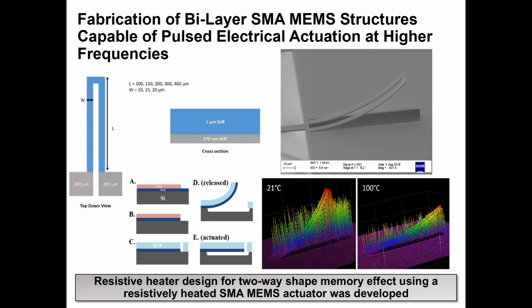So the SEM image in the upper right shows the curvature radius of the released actuator, exhibiting an out-of-plane curl, consistent with the model predictions shown earlier. A laser confocal measurement was used to quantify the curvature radius. In the lower right figure, it shows the actuator in the curled released state at room temperature at a radius of 178 microns, and then flattened out substantially to an actuated radius of 789 microns when heated above the austenite phase change temperature to 100 degrees.